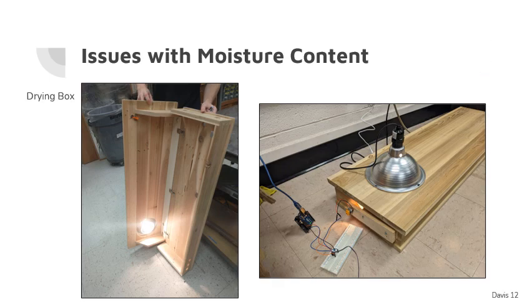So I would like to now outline, out of all of our challenges in the process, one of our most major ones was the moisture content present in the palm fronds we received. Florida's humid. Palm fronds are inherently a damp sort of wood product, and by the time they were collected and shipped over here, they did not dry out. So we had water present in the shipping box, lots of water still hydrated within the palm fronds themselves, and so we worked to come up with a solution to that, and that was our drying box, because we didn't want moisture in our final planks.